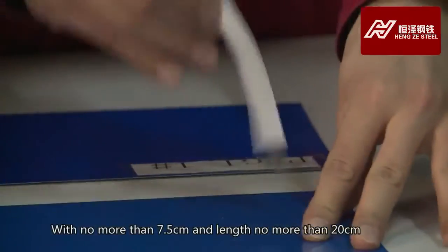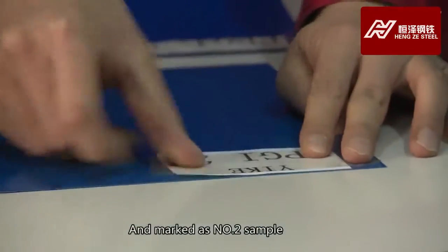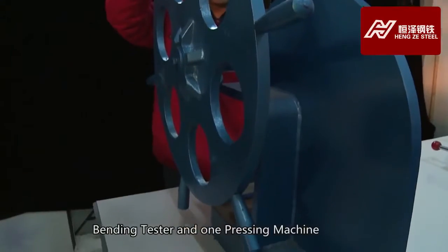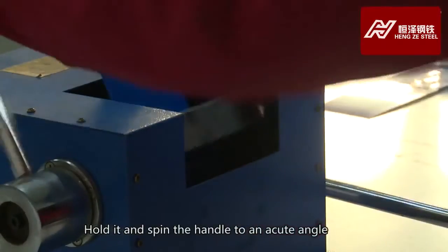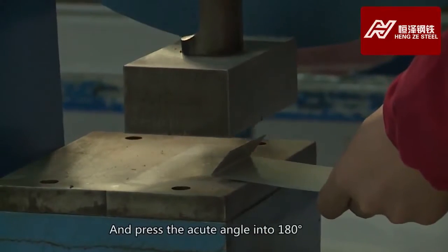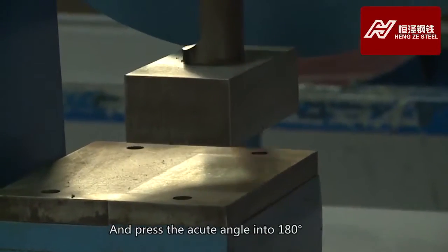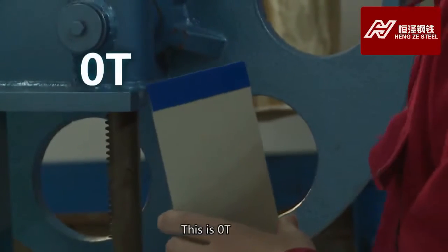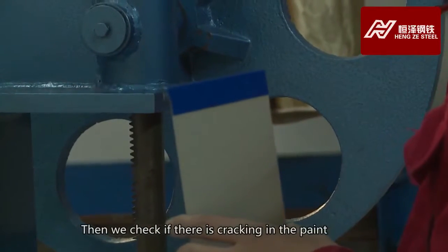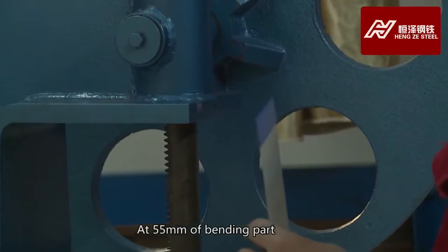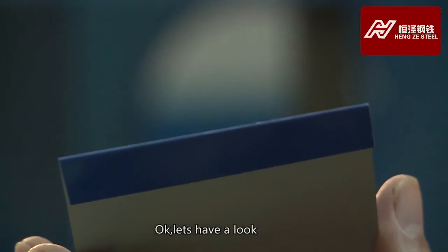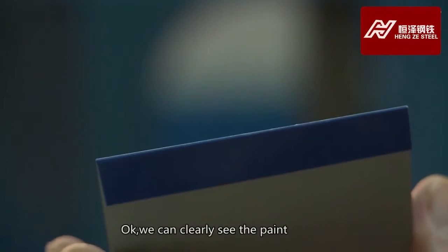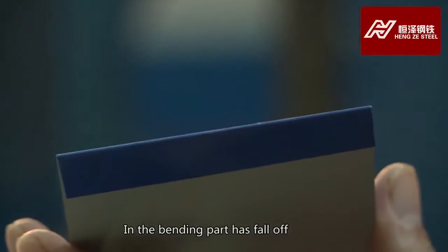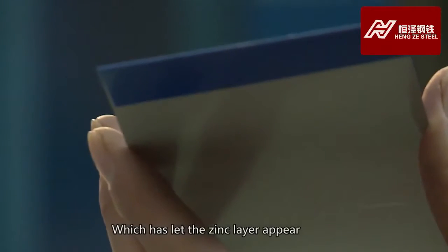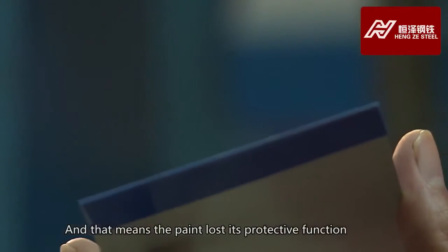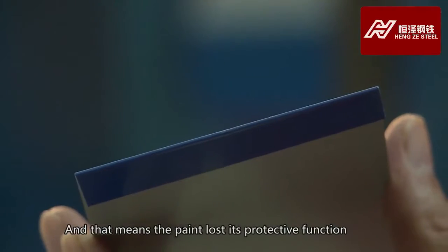Cut a length of no more than 20 centimeters, marked as the number 2 sample, and use a pressing machine. Hold it and spin the handle to an acute angle, and press the acute angle into 180 degrees. This is 0T. Then we check if there is cracking in the paint at the 55 millimeters of bending part. Okay, let's have a look. We can clearly see the paint in the bending part has fallen off, which lets the zinc layer appear. That means the paint lost its protective function.